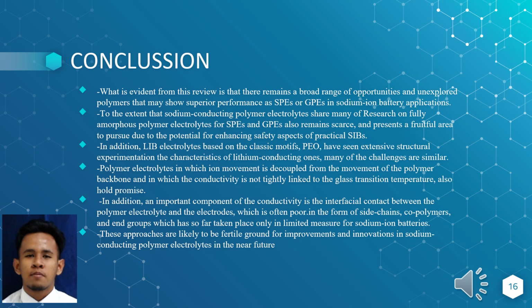In addition, an important component of the conductivity is the interfacial contact between the polymer electrolyte and the electrodes, which is often poor. Improvements in the form of side chains, copolymers, and end groups have so far taken place only in limited measure for sodium-ion batteries. These approaches are likely to be fertile ground for improvements and innovations in sodium-conducting polymer electrolytes in the near future.